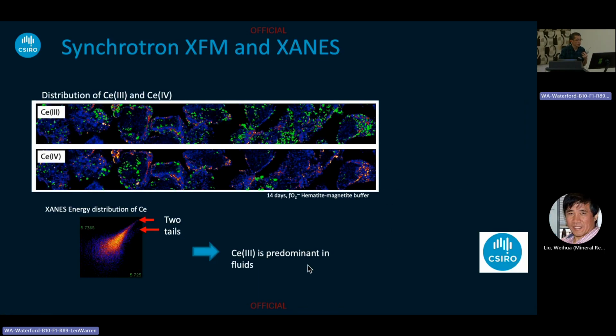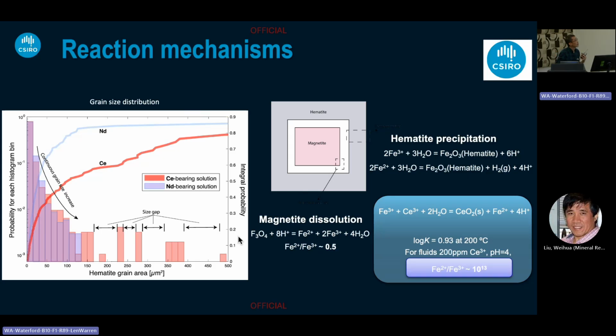So what does it mean? Firstly, we put the sample into the synchrotron. We want to understand the redox state of cerium, because it is capable of redox changes. The cerium 3 originally put in the solution is possibly being oxidized to cerium 4, which is not mobile in geological fluids. We see that cerium 3 is more homogeneously distributed in the minerals, versus cerium 4, where you only see some random hotspots here and there instead of everywhere. So cerium 3 is still predominant in the fluids as they grow.